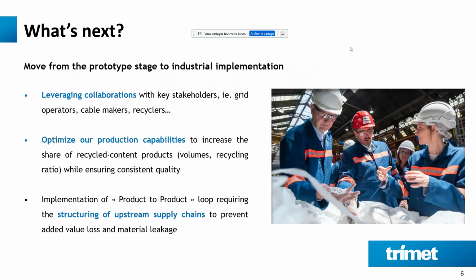And now if we look at the next step, what is important to us is really to move from this prototype stage, I would say, to really industrial implementation, which we already did. And over the 2 years, with an increase of sales of wire rod with recycling content to our customers. For this, we have to work upfront on the value chain to ensure that we get the material, because this scrap coming mainly from the TSOs is of a very high quality, can be used by anyone, and has a very high value.